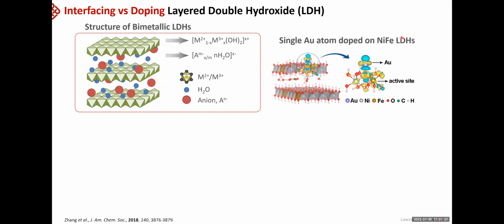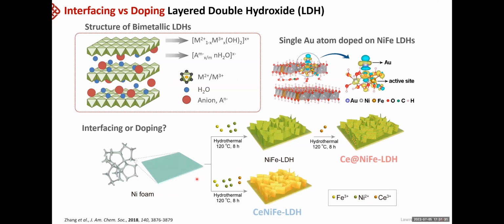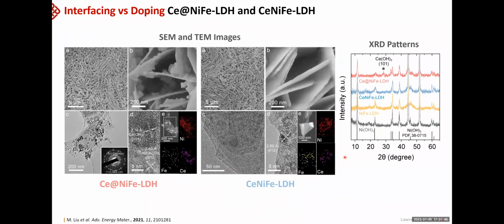The last part of my talk is actually we were interested to know which one, interfacing or doping, is more important in terms of determining their property? So due to the time, I will quickly go over. In order to understand which one contributes more to the improvement of OER activity, we chose nickel iron LDH, and we doped cerium in a different way. By controlling the synthetic condition, we homogeneously doped the cerium to the nickel iron LDH, or we formed some sort of interface by forming the cerium hydroxide species. As you can see, one type shows very nice interface with a cerium hydroxide species, but the other one is still a smooth surface with a nice layered structure.